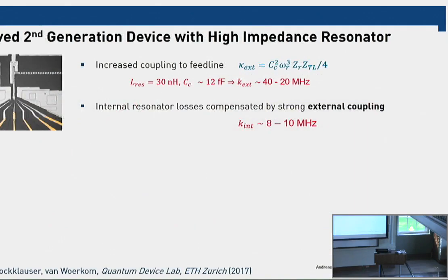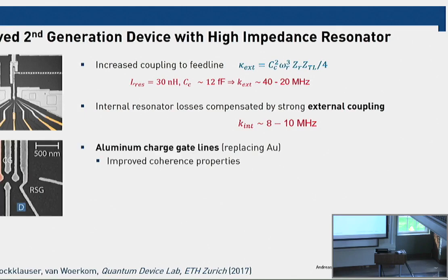Okay, so we thought about what can we do better about our experiment, and we made a second generation device. And in the second generation device, we improved some basic properties. So for example, we made the resonator a bit more strongly coupled to get better signal to noise ratio. And we got a little bit better Q of the resonator. But what improved maybe most was the fact that we changed the design of our double quantum dot a little bit. And we moved away from using gold gates, which was something that people were doing for 20 years, more or less, in these structures, and tried superconducting gates. And that's also something that Jason Petta did.